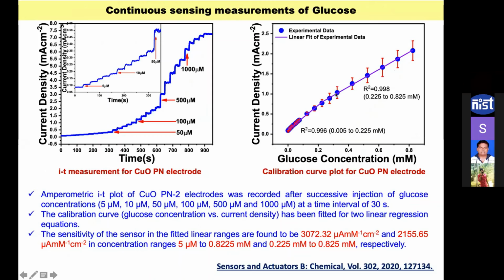So here we got two different regions. This is linear from 0.005 millimole to 0.225 millimole in one region, and another from 0.225 to 0.825 millimole. And the sensitivity of those sensors is quite higher than the earlier gold coated samples. So this is 3072 microampere per millimole per centimeter squared.